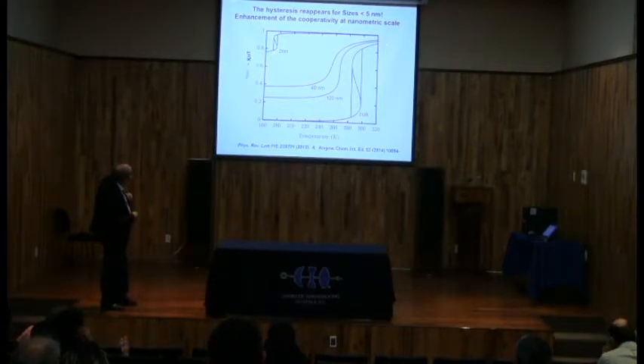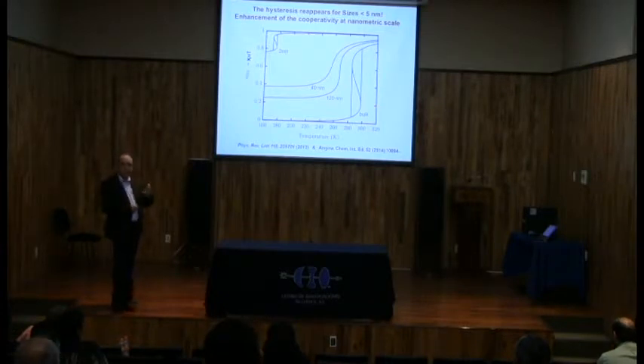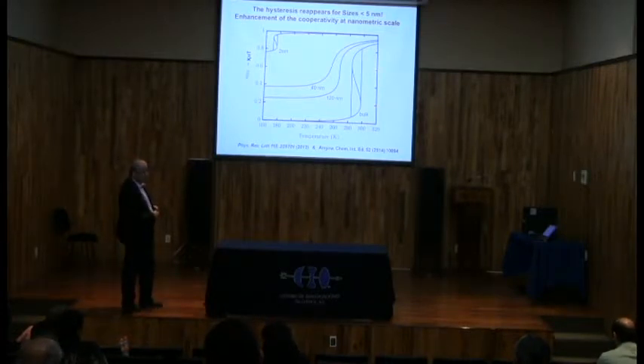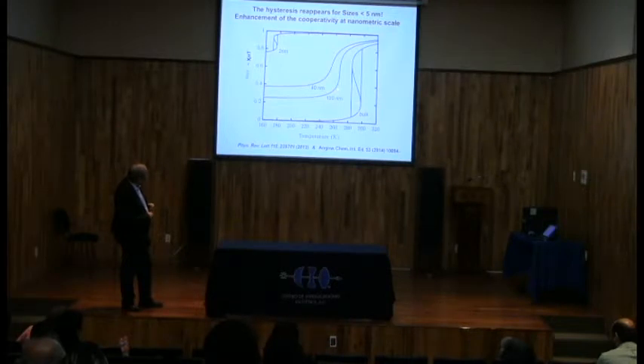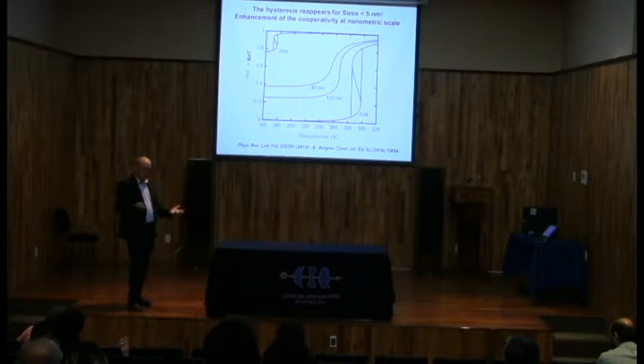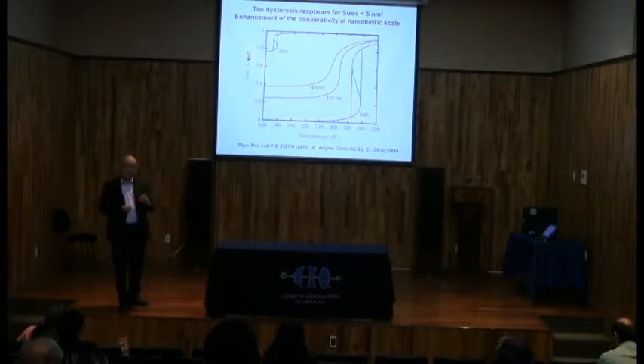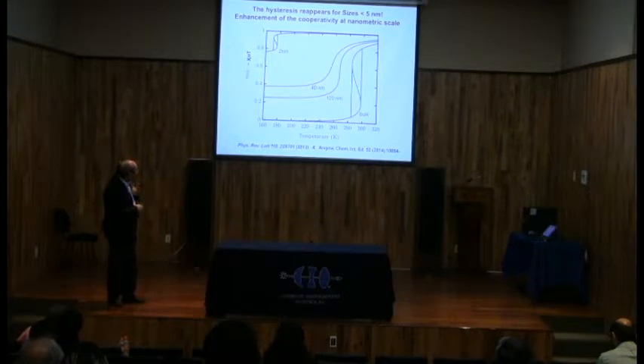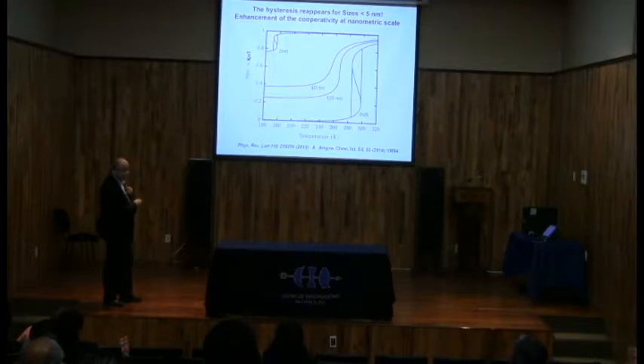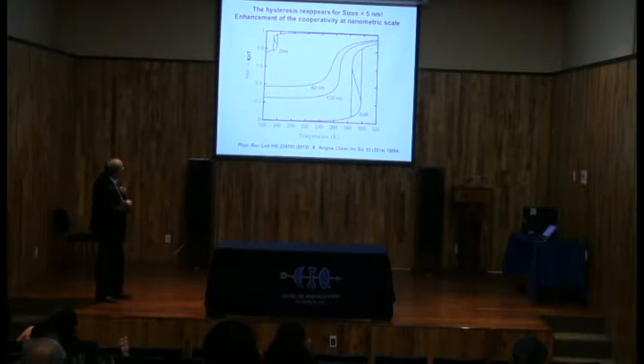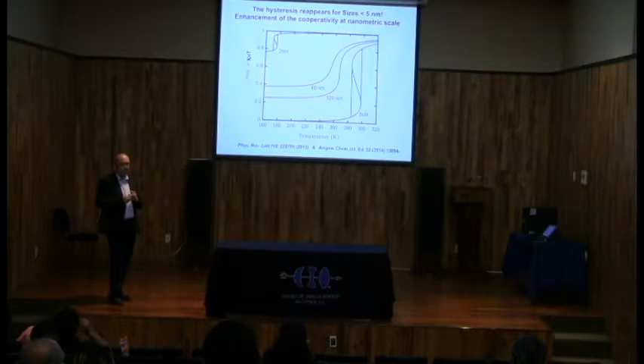Okay? You see that in the bulk material, macroscopic materials, you have a hysteresis loop, first order phase transition hysteresis. If you decrease your size, you see when you go from the bulk material to 120 nanometers, you are cutting the interactions, so then you lose your hysteresis loop. You see, you have a gradual crossover. What was strange and very interesting in such experiments is that when you go to very low dimensions, like 2 nanometers, you see that the hysteresis appears again. It reappears.